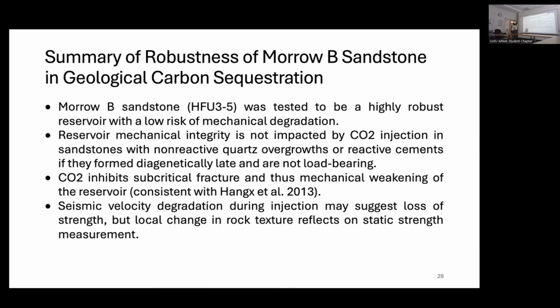Okay, I believe we went through all the static and dynamic measurements and observations. To conclude, we think Morrow B sandstone, the formation we're interested in for CO2 injection, was tested to be a highly robust reservoir with a low risk of mechanical degradation. And we also think the reservoir mechanical integrity is not impacted by CO2 injection in sandstones if there are non-reactive quartz overgrowth or reactive cements, if those cements and overgrowth formed late in the diagenesis history, or if they're not load-bearing. And we also found that the CO2 inhibits subcritical fracture, so mechanical weakening of the reservoir can also be prevented in this way.